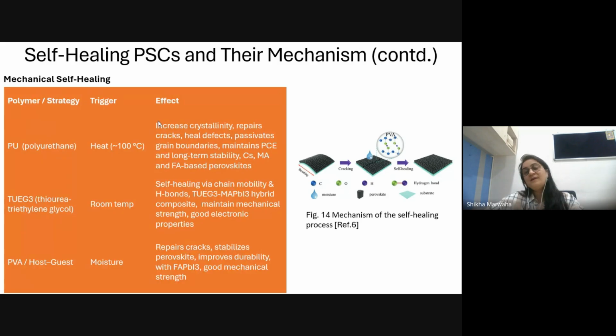Now, by self heal, I mean that it will repair itself. By repairing its cracks, it will heal its defects, it will passivate its grain boundaries, and also maybe with duration of time, let's say the power conversion efficiency has decreased, but after certain time it will retain 90 to 91% of its initial value of power conversion efficiency. So yes, this can be used.